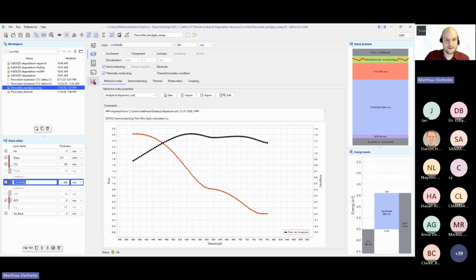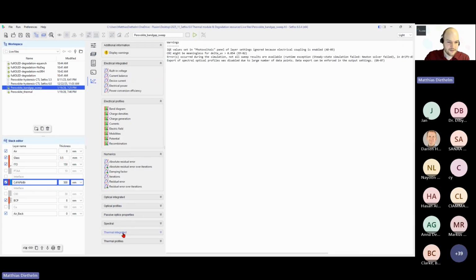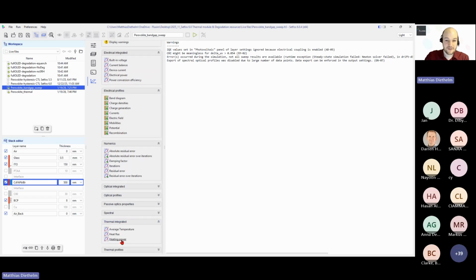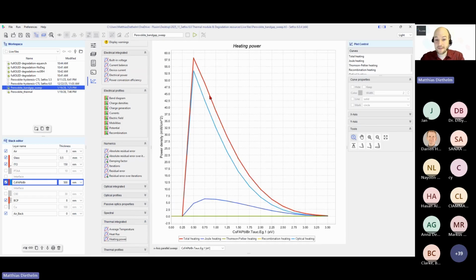So what we're looking at now in the results is directly at the generated power, where we now can split up the heating we saw before and look into the different factors. Now in this simple model, the biggest part, or in general, the biggest part is the thermalization. But even in the simple model with no recombination heating, for example, we see there is this Joule heating, which you cannot avoid, as you need to extract the charges.